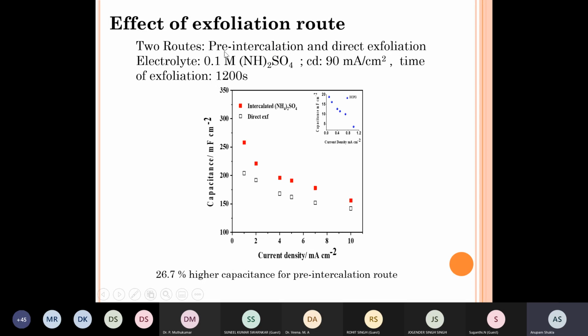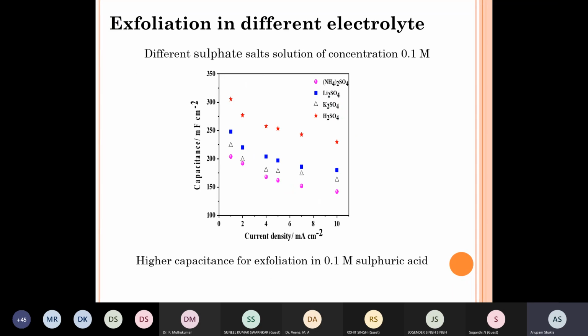So we followed two synthesis routes. One is pre-intercalation of electrolyte and then exfoliation. The other one was direct exfoliation. This was done in ammonium sulfate solution at 90 milliampere per centimeter square for 1200 seconds. And what we see is that for the pre-intercalated route, the areal capacitance that we obtained was about 25% higher than the direct exfoliation route. So we continue to use the pre-intercalation route for synthesis.